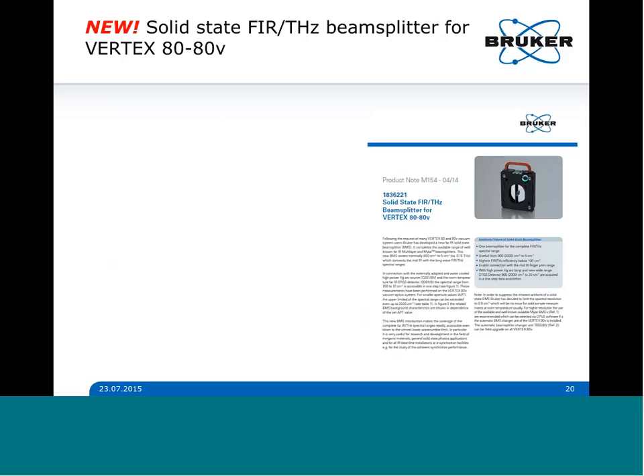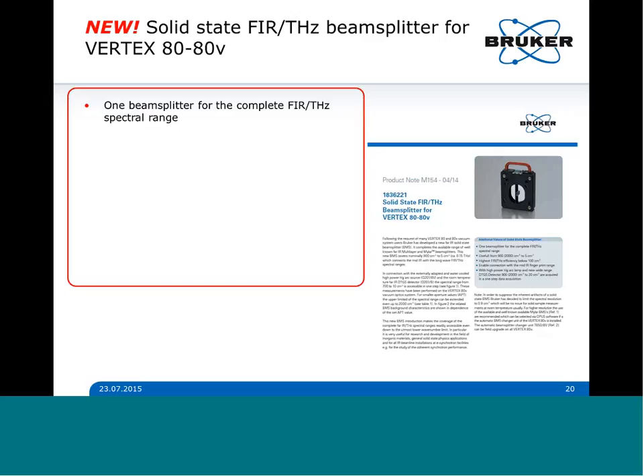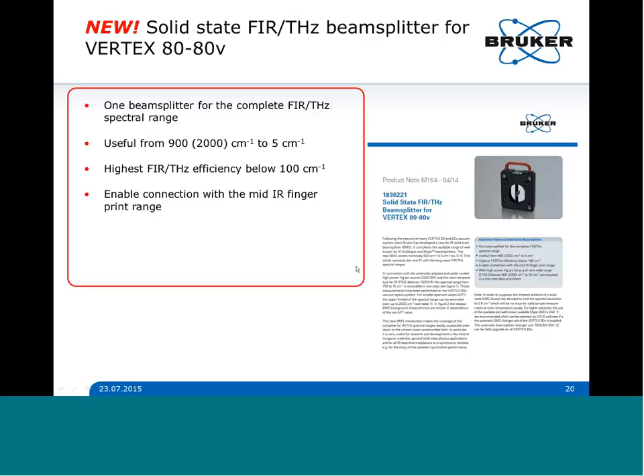Now, only for the far infrared and terahertz range, we have a new solid-state beam splitter for both VERTEX 80 purge spectrometer and vacuum spectrometer. Here you see the product note again, and with this one beam splitter, you can cover the complete far infrared terahertz spectral range, and the useful spectral range is from 900 down to 5 wave number. The efficiency below 100 wave number is quite high, and actually that connects perfectly the mid-infrared fingerprint region with the far infrared region, because it goes up to 900 wave number.